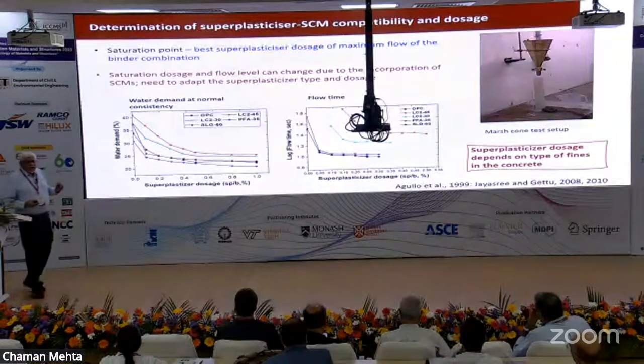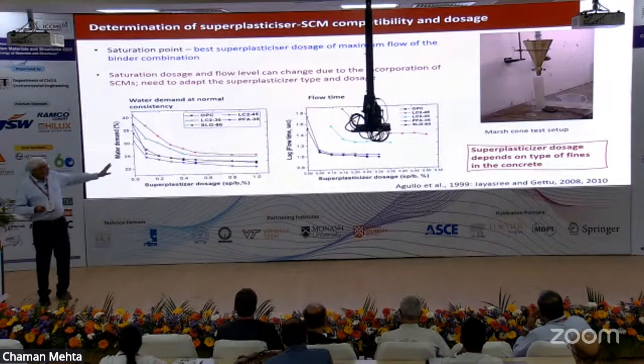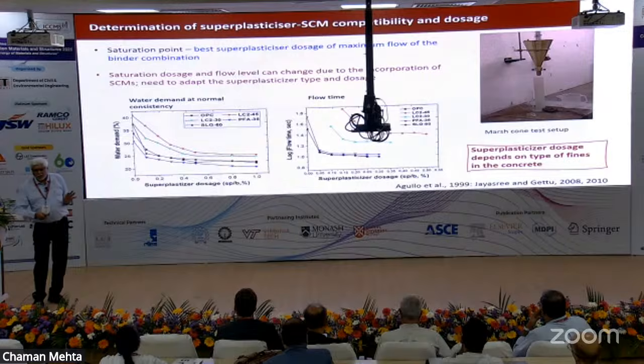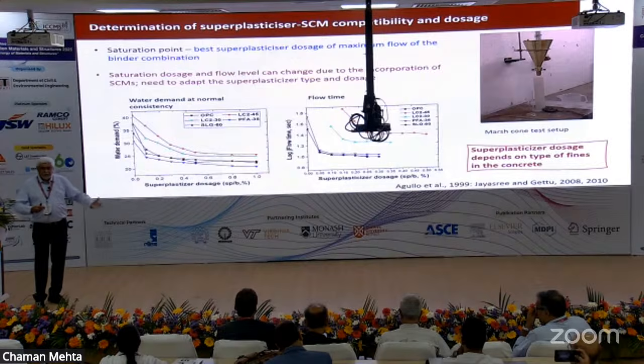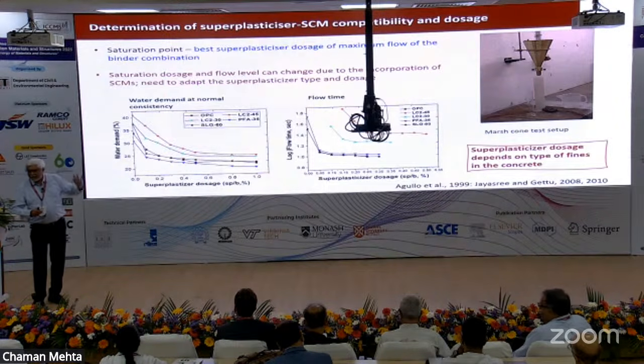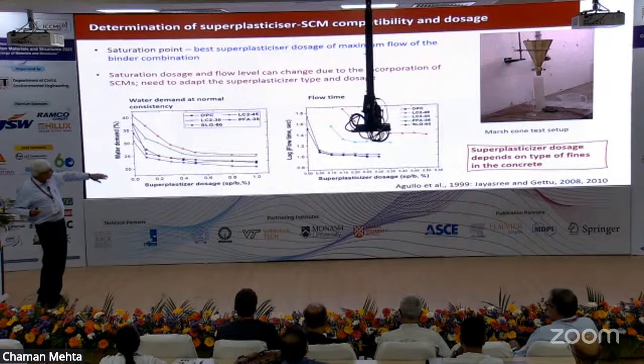So, and we have to keep things simple. So we use this very simple test called the Marsh cone test. It's so simple that people said this will not work. And we had to do a lot of rheology, sophisticated tests to show that this works. So what this does is you take 1 liter of cement paste, pour it into the cone and measure the time taken for half a liter to go through. Then that's one of the points in that curve on your right. And you can see that these curves shift.